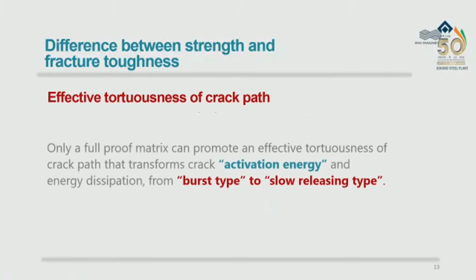So in R&D terms, we call it effective tortuousness of the crack path. The crack is there, so I'll have to inhibit the crack in such a way that it feels the most resistance in propagating. So what the matrix does, it transforms the crack activation energy and energy dissipation from a burst type to a very slow releasing type.